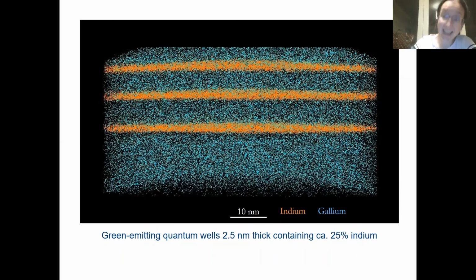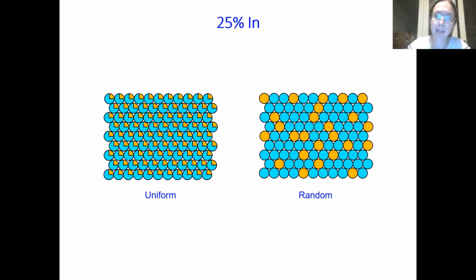I'm not showing you any of the nitrogen atoms in this indium gallium nitride for the same reason, because the nitrogens just dominate the whole picture. I am, however, showing you the indium atoms, all of them, and we can see our quantum wells, okay, about 2.5 nanometers thick, as we've said before. Now, you can't really look at this and say, is this quantum well perfectly uniform? Because this is actually looking through quite a big wodge of the quantum well. And it's also not necessarily great to be judging these things by eye. So what we do is some mathematical analysis.